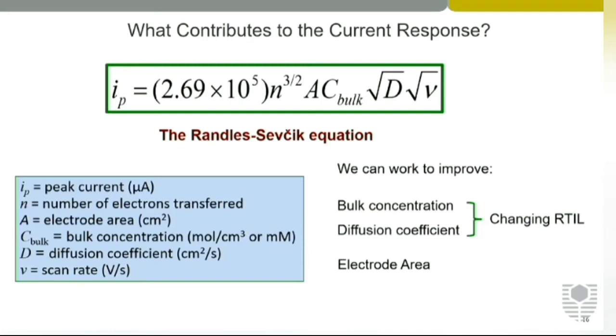And so what we can do in our experiments is to improve a couple of these things. So the bulk concentration, which is the solubility of the gas in the liquid, and also the diffusion coefficient, how fast it moves to the electrode. And we can do that by changing the ionic liquid structure. We can also improve the current response by using larger electrodes, so we can change the electrode area.